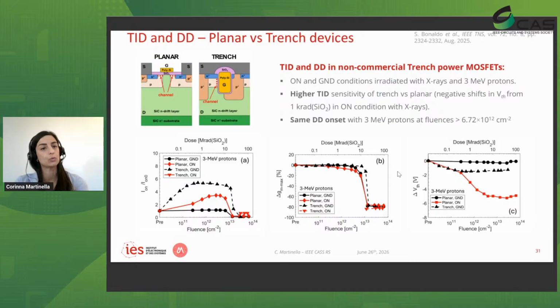We also looked into different architectures, not only planar, but also trench device. In this case, it was a non-commercial asymmetric trench device. But similar observations were also made in literature for commercial components. And in our case, we saw that both with X-rays and also 3 MeV protons, the trench device was more sensitive. For example, if we look here at the delta of the threshold voltage, we have in black with the round dots the results from planar device in ground condition, and in the triangle the results from the trench device in ground condition. And similarly for the on-state current. So we can see how things in this case were worse with the trench architecture. However, once again, the onset for the displacement damage was observed to be similar.